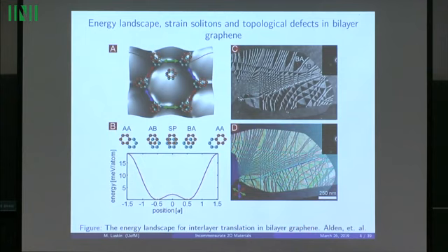So we see, right, this is the high energy. That's when, say, the red layer is sitting right on top of the blue layer. And then these here represent the AB and BA states. So this is our energy landscape. This comes out to be one of the simplest bistable systems you can think of, when you have two states, right? And you're trying to minimize, you normally get some kind of patterns. Okay. So we'll see how that goes.